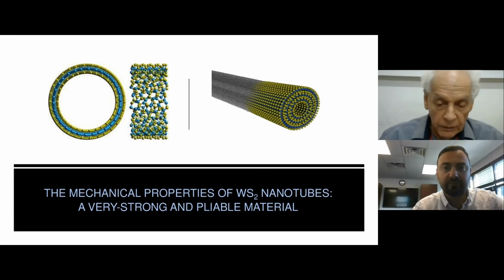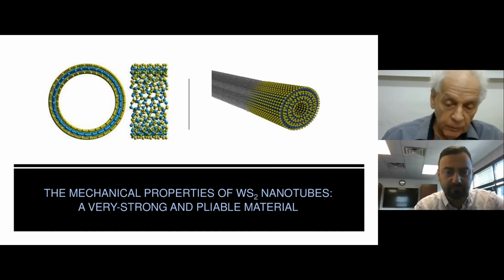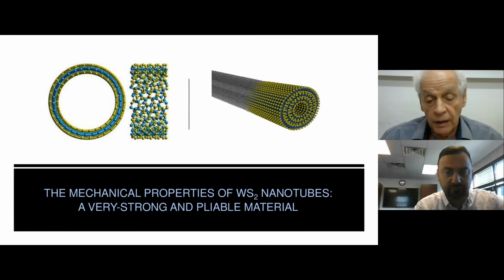They are very stable. Of course, if you heat them above 200 degrees C in dispersion or solution... but you cannot heat them to 200 degrees C in solution. In air, if you heat them, they start to form sulfides and tungstates, at a temperature of about 300 degrees, actually even below that, but the rate is very slow.